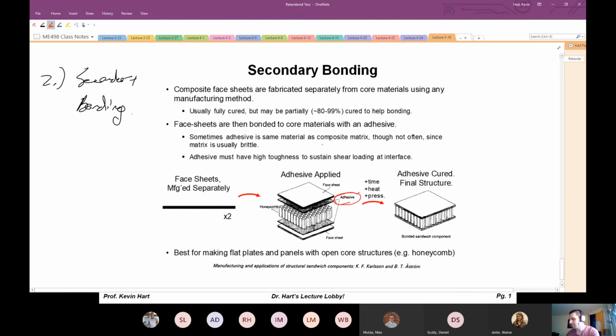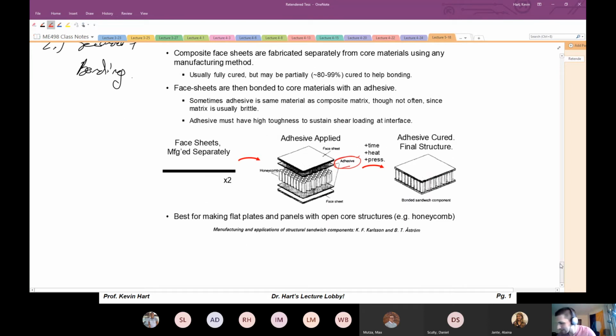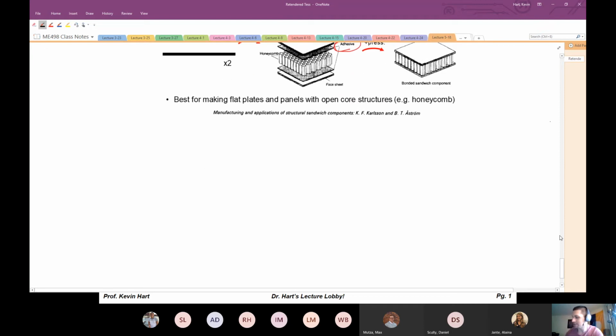All right, so typically the adhesive here is not the same as the composite matrix, though sometimes it is. It has to have a high toughness to sustain that shear loading at the interface should it occur. Okay, so if I provided shear in this general direction, that adhesive has to hold that loading that I'm applying with that sort of shear force. And we know the brittle epoxy matrix is not so great for that.